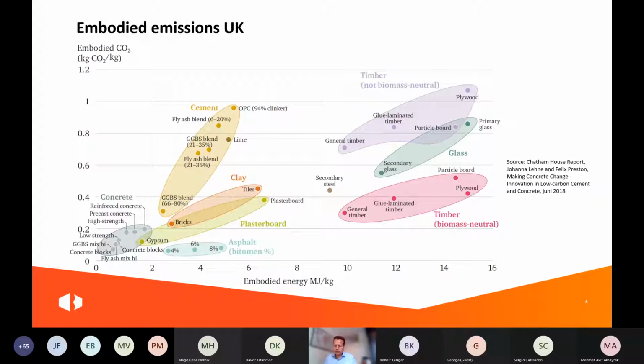Now, of course, if you're going to look at alternatives for cement and concrete, then we have to look at the CO2 profile of alternatives. Here you have a picture of different materials, including asphalt. And here you see that cement has quite a high CO2 profile compared to other materials, but of course cement is only used for a few hundred kilograms in a cubic meter of concrete.